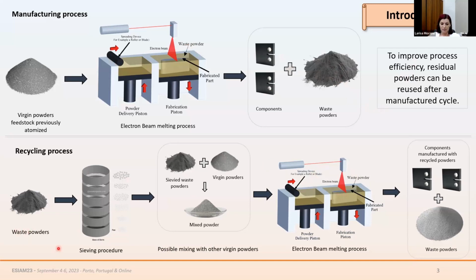So this waste powder can be firstly sieved in order to narrow the particle dimensions, and also to eliminate any elongated particles, bonded particles, and so on. And then it is also possible, but not mandatory, to mix this sieved waste powder with other virgin powder, for example, to keep low the oxygen content. And then starting with this mixed powder, another manufacturing cycle will start, at the end of which we will obtain other components and, of course, other waste powder.